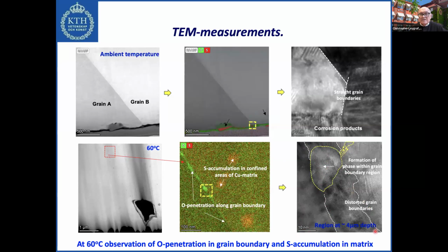And as a result of the oxygen penetration into the grain boundaries, oxygen reacts with the surrounding copper and forms phases. You can see that here, nano-sized oxide particles. You can see from these lattice fringes that this is really a crystalline phase, and it's something that looks similar to a cuprous oxide. And because of that, there is an expansion of the grain boundary region, and the grain boundary becomes distorted like this. And you can imagine that if you have a distorted grain boundary region, the number of defects will increase considerably.